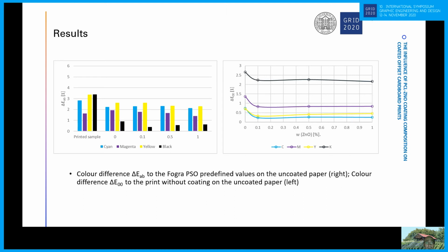We can see on the left that on uncoated paper, the differences in comparison to the FOGRA PSO predefined values are lowered when the coating is applied, for all the inks except the magenta. And on the right side, we can see that the differences are highest on the black print, while on the others it is lower than 1. On both sides, we cannot see really that the addition of zinc oxide is leading to some different color changes.